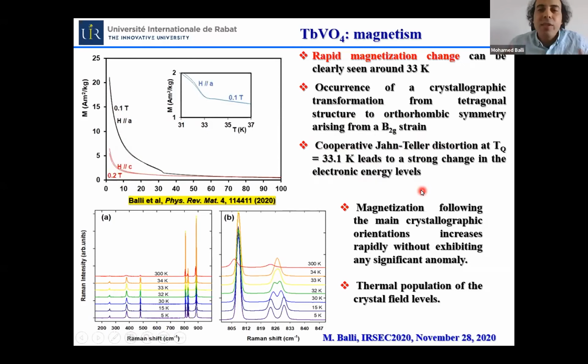So this crystallographic transition, which is associated with Jahn-Teller cooperative distortions, is confirmed by this Raman scattering data reported in this figure, where we can see that under temperatures of 33 Kelvin, we can see clearly splitting in some energy levels.